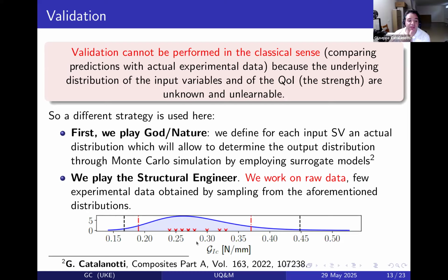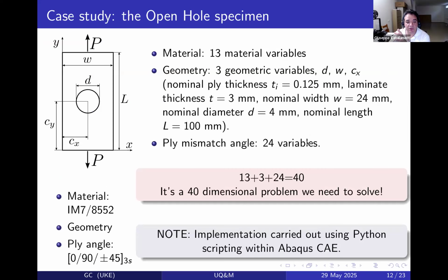For example, for the mismatch angle, how do you do it? You do a CT scan of your specimen, and then you have an approach to measure the misalignment angle. In that case, it's extremely easy from just one scan to get 300-400 values. There I have assumed a lot more. Strength is easier to run than fracture toughness, so I assumed about 10 or 15 specimens. So I used my engineering experience to have some reasonable data points to start with.